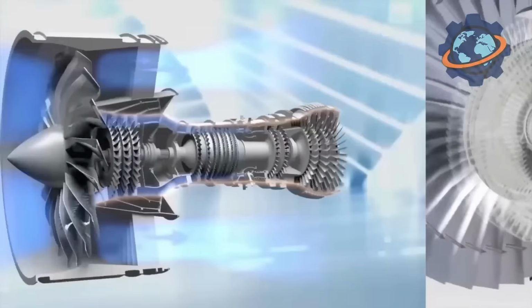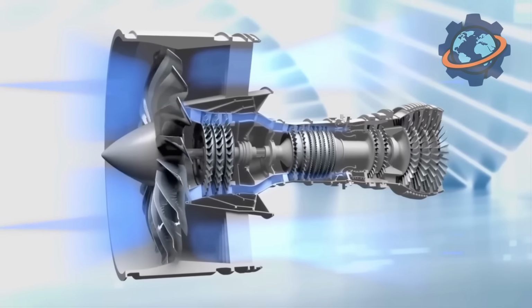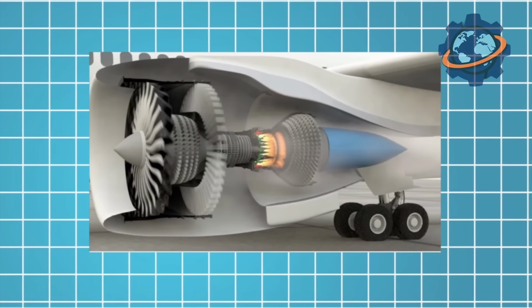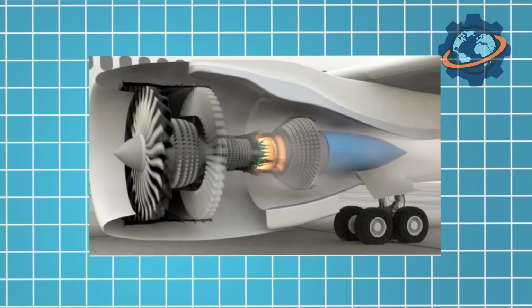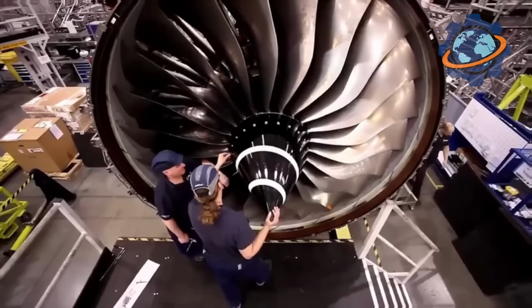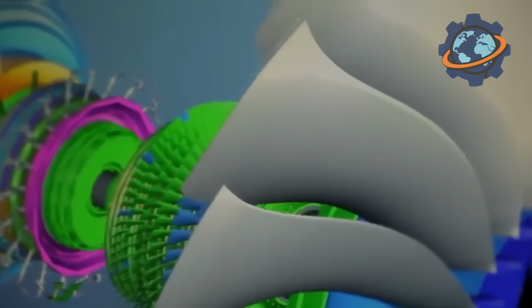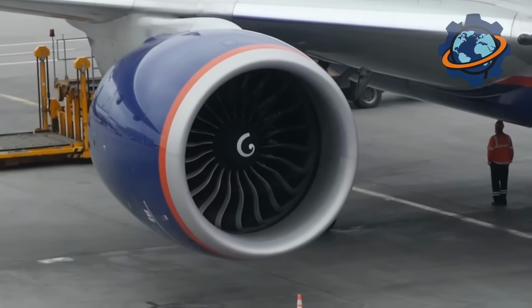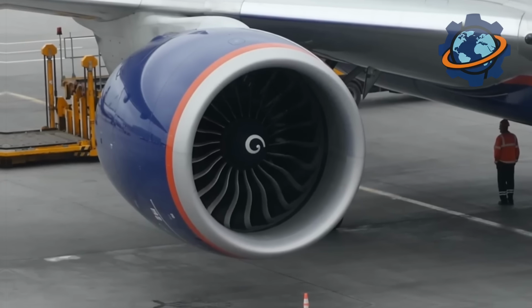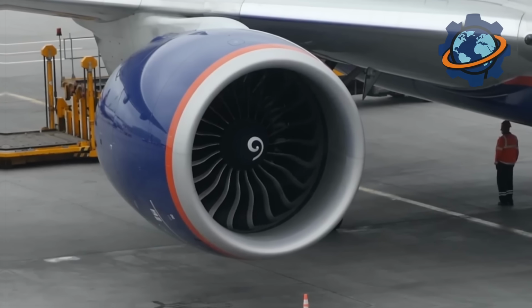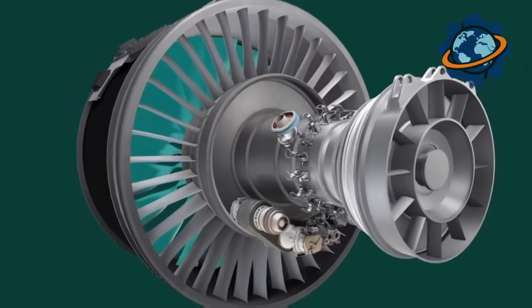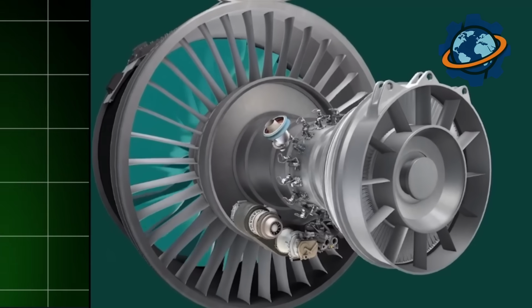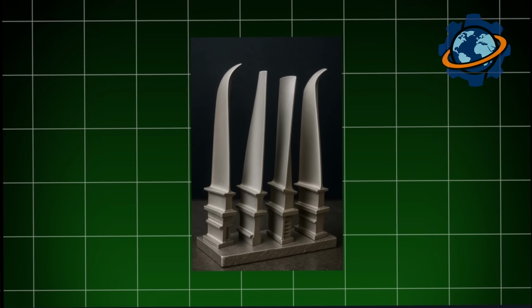This cooling air, already compressed to 400 degrees Fahrenheit, seems hot by human standards but runs ice cold compared to the 3,000-degree combustion gases outside. Combined with ceramic coatings reflecting heat like mirrors, the actual metal temperature stays below 2,000 degrees. Hot enough to glow orange, but survivable. From molten metal to flying miracles, cycle completes.